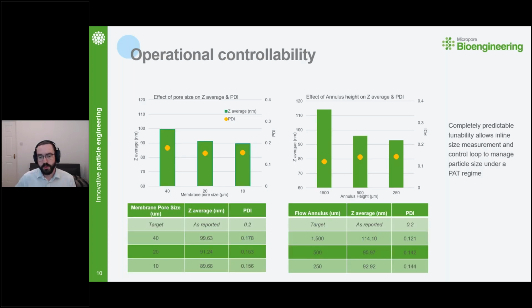Outside of just controlling via the total flow rate, we've also been able to demonstrate control by changing the pore size of the membrane and the size of the annulus within the device as well. Because what if you wanted to produce those 100 nanometer particles, but at 1.2 liters per minute, as we showed on the slide before? And that's where these other levers come into play. That's where being able to change your membrane pore size, being able to change the size of that annulus, lets you achieve the size you need at the flow rate you need. It decouples those two indicators.